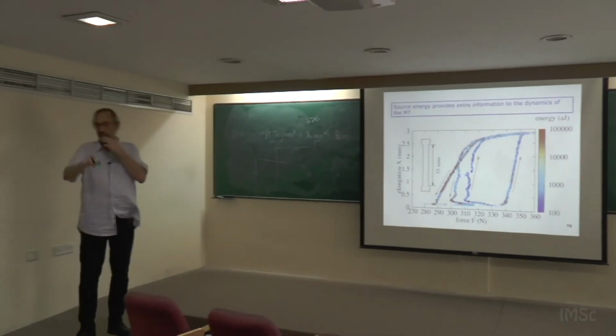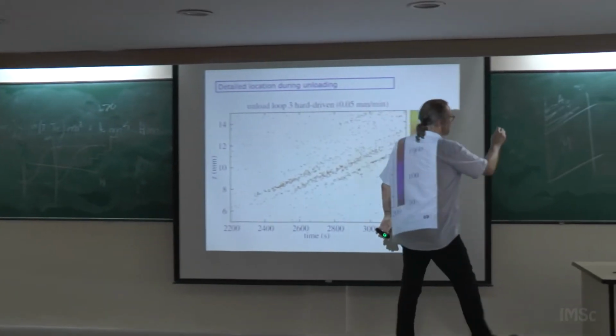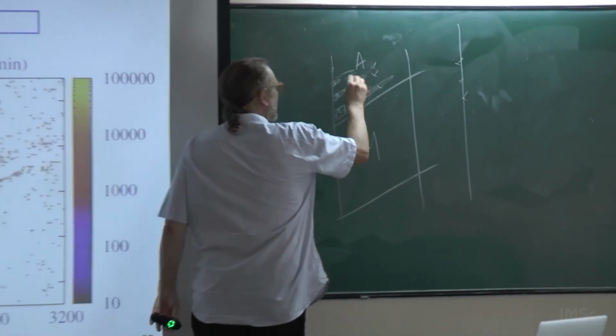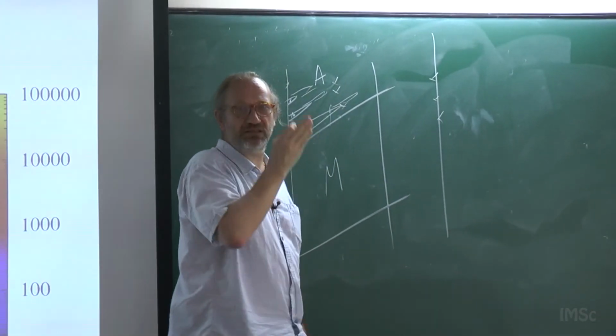Any more questions? Yes. So the lines in the earlier plot, do they correspond to the shear bands or the slip lines? No, none of the two. This is a first order phase transition. This is a different phase. This is martensite, and this is austenite. So it's the martensite advancing in the austenite.